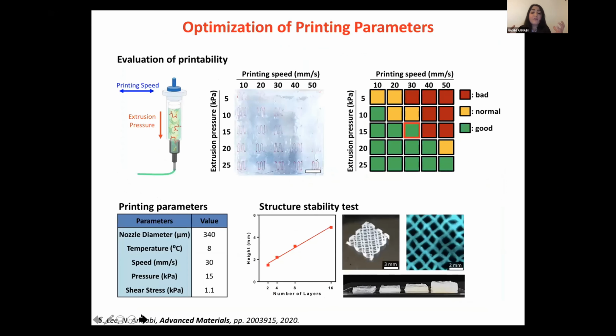So basically, before we form complex structures based on these bioinks, we did lots of experiments to optimize the printing conditions, including extrusion pressure, printing speed, and also controlling the temperature. The goal of this experiment is to form a structure with better resolution. And as we optimized these conditions, we were able to form multi-layer structures based on our bioink. Basically, we can combine this through layer by layer assembly. We can control the thickness of the structure that we bioprint.